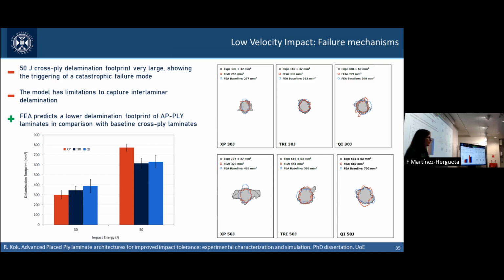In the literature, you will find micromechanical approaches that are very, very good at capturing this interlaminar delamination, but they use massive amounts of elements, and they are more indicated to be used at materials level. So at this point, if you're going to investigate AP-PLY laminates, you need to make a decision on whether you're going to investigate at materials level, where you might want to go for a micromechanical approach, or whether you might want to develop tools for industry and stress analysis, where you might want to go for one of these macromechanical approaches.